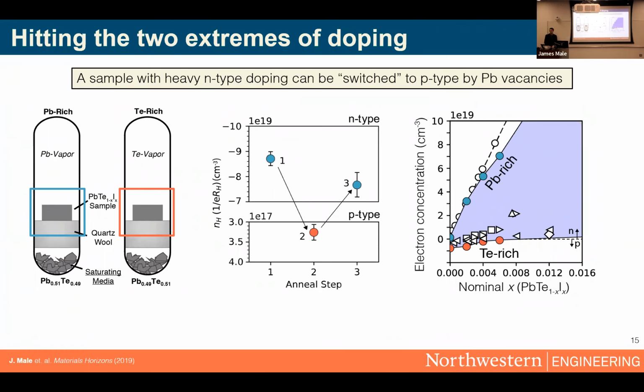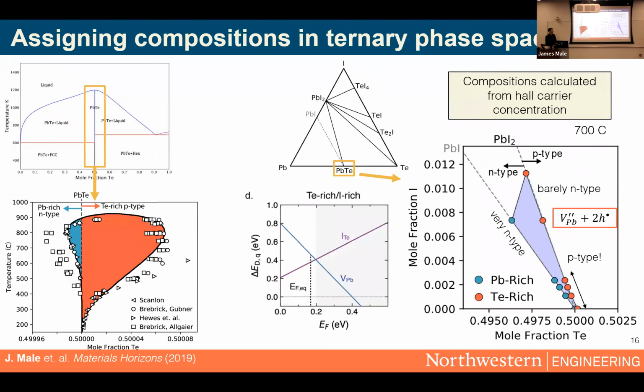Sure. So a bit of a follow-up on Jenny's question. You measure directly this very precise level of doping. Yeah, so we use Hall carrier concentration measurements, which aren't perfect. So, you know, there's a kind of a corollary here that this is a sketch. Hall carrier concentration gives you a sense of the number of dopants you have, but it also depends somewhat on the band structure. So potentially these things should all be reduced by like 1.2 or so.